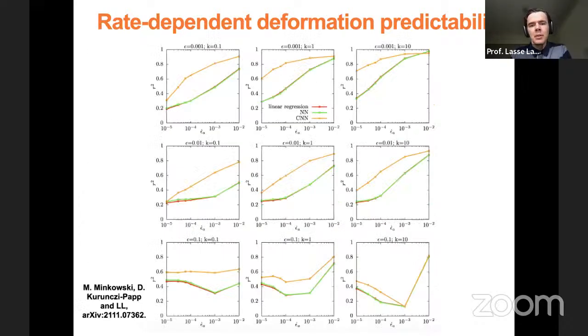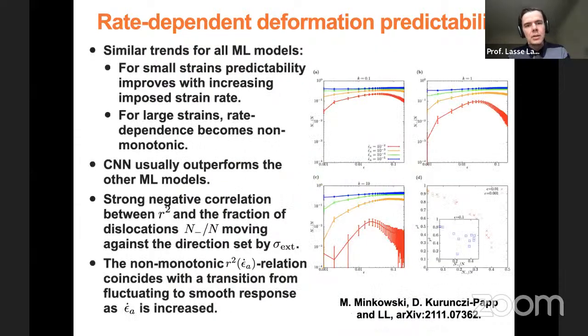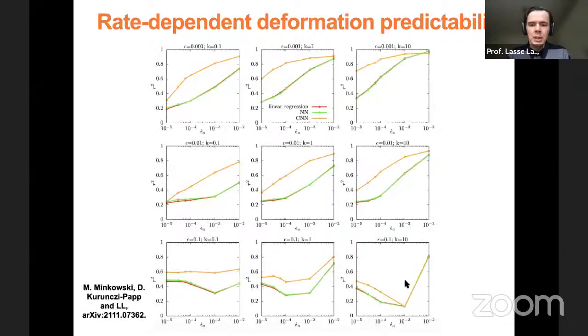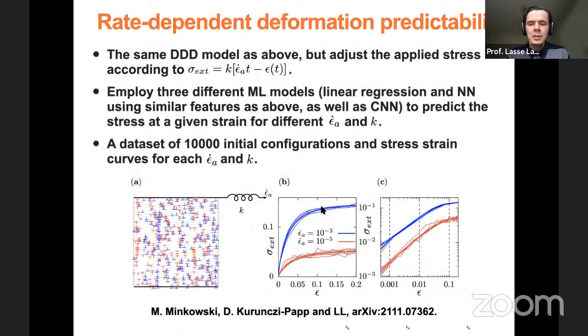So yeah, now we try to, of course, make some sense out of all of this. So why do we have these trends with the strain rate for the R squared? So the idea, first of all, is that if you change the strain rate, you change the nature of the dislocation dynamics. For very large strain rates, because of the size effect that I already showed you here, if you have a larger strain rate, then at a given strain, your stress will be higher.